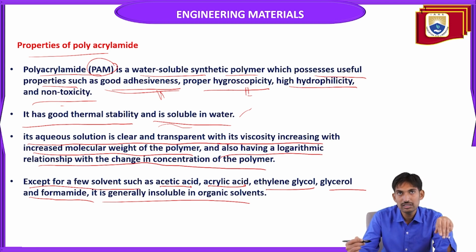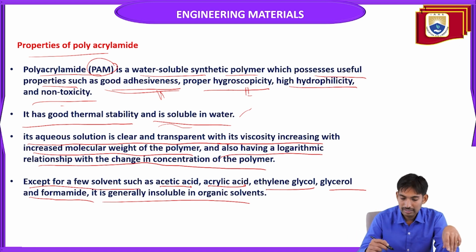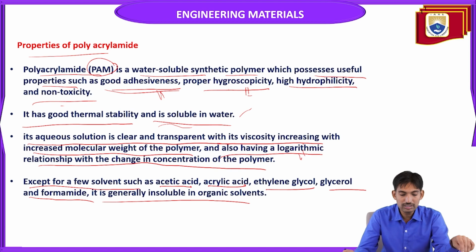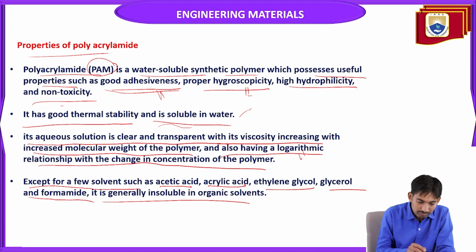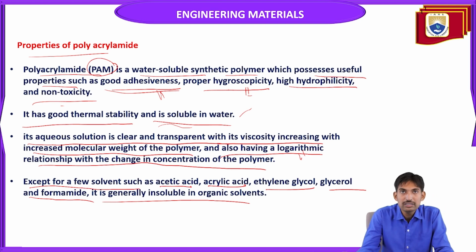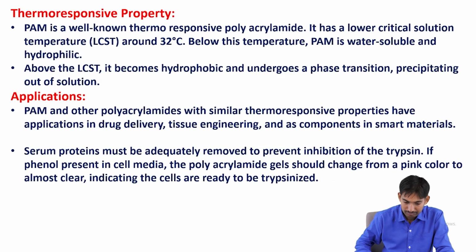The viscosity of PAM increases with molecular weight, and it also has a logarithmic relationship with the change in the concentration of the polymer. Except for a few solvents such as acetic acid, acrylic acid, ethylene glycol, glycerin, and formamide, it is generally insoluble in all other organic solvents.